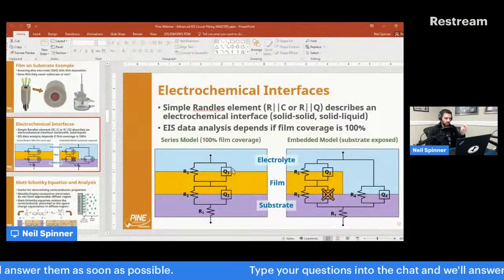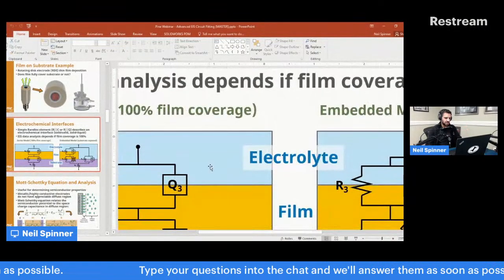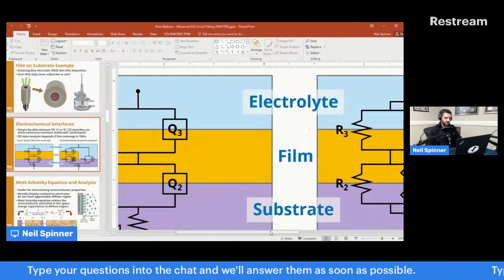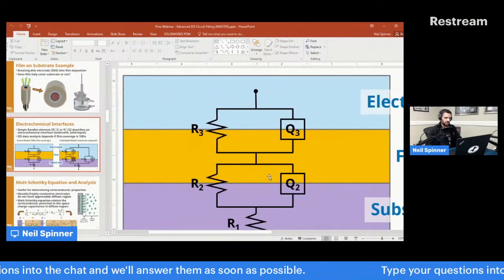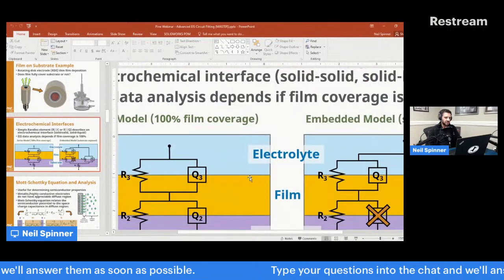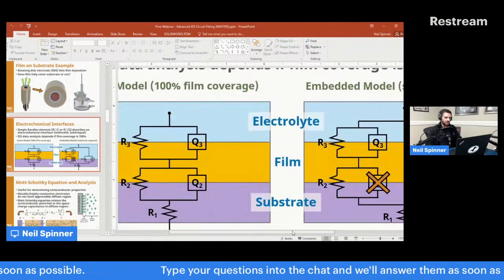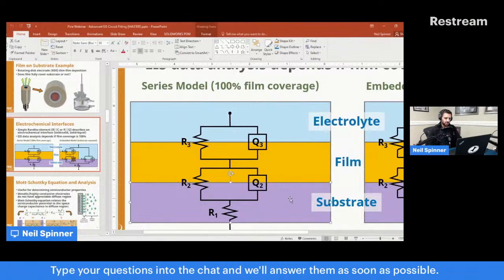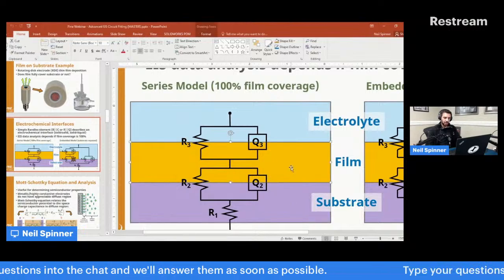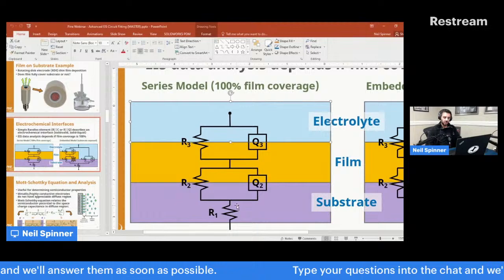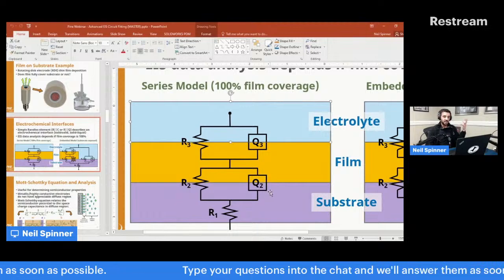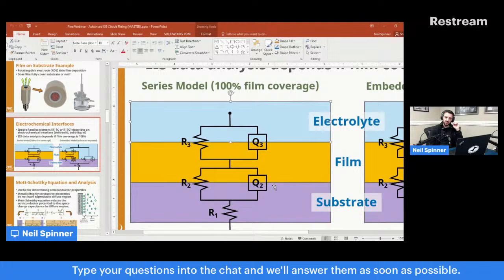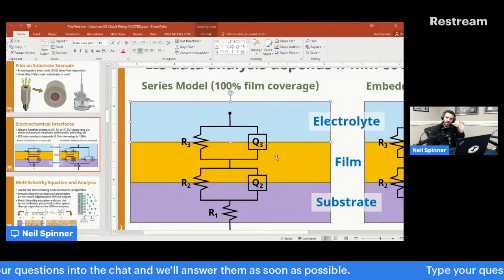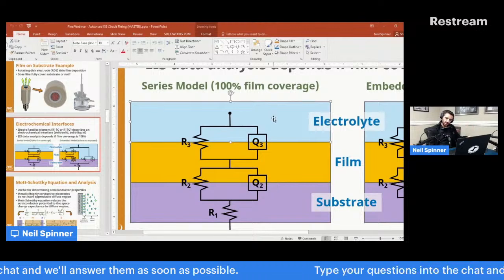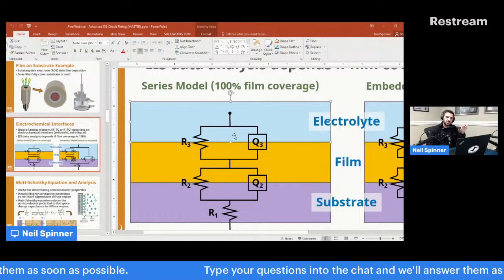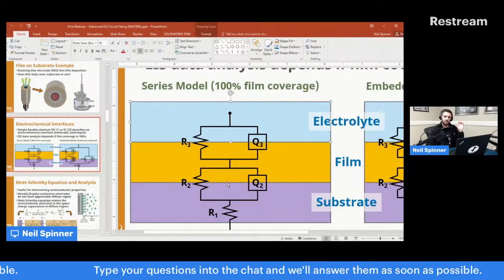So look on the left here. This is the situation of a series. My film is fully covering my substrate, so I have two distinct interfaces, which is probably leading to your two time constants. This is the substrate, this is your metal film, this is your polymer, and then you have an electrolyte. In this case, if I'm not porous at all, my polymer is solid, and there's no interaction between the electrolyte and the underlying substrate, then I have two in series. That's like the progression that you have here.